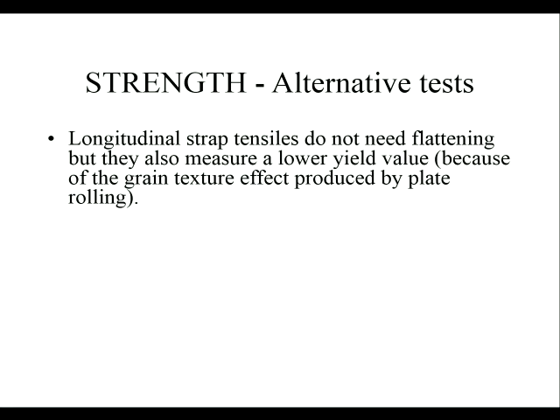So the other thing you can do is do a longitudinal test. So instead of from around the circumference of the pipe, along the length of the pipe, they don't need flattening. But because of the way that the pipe's been made, they measure a lower yield strength. So again, there is a problem with the data because it's not measuring in the direction of loading, and it will come out slightly lower. But again, if it's lower and it still meets the specification, that's probably all right.